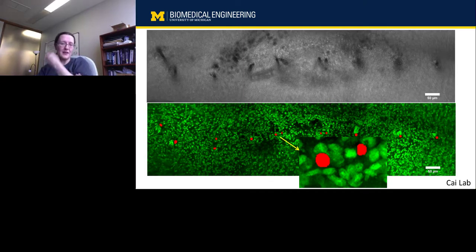And I should say that the little flecks of carbon, sometimes they stay in the tissue slice, sometimes they don't. The key is actually knowing where they are. Because once you know where the hole is, you know which hole comes from a carbon fiber rather than a capillary, it's really obvious to follow. So as soon as you know the location or roughly the area that it should be, you can find the hole, and my students can circle the hole all the way down to the tip of the electrode, and it's just slightly larger than the carbon fiber itself.